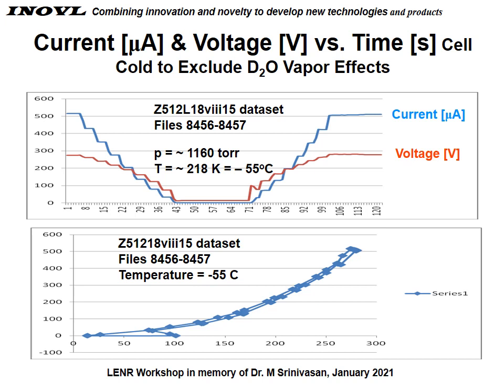As another test to see if we're getting any relative humidity, we put the cell in some dry ice that took the temperature down to minus 55 degrees C. At that point, there should not have been any water vapor in the gas. And we conducted the test, and you see the plots are very similar to the ones that you saw previously. And down below, you see the plot of current versus voltage on the lower trace.